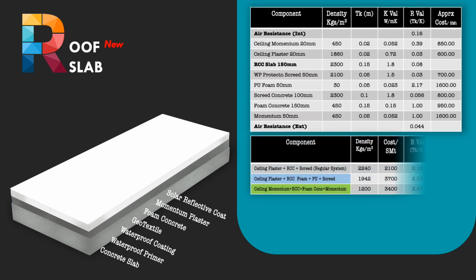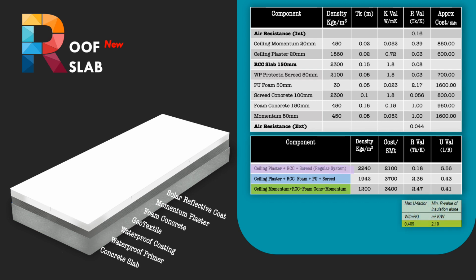System 1 is the conventional system with cement plaster for interior ceiling, waterproof coating over slab, protection screed of 50 mm, followed by slopes with screed concrete. R value of system is 0.18 and U value 5.56, which is nowhere close to recommended standard of minimum 2.1 and maximum 0.41 respectively.